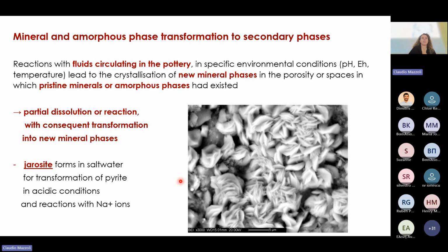And this is the case, for instance, of jarosite, which forms in salted water by transformation of pyrite under acidic conditions and by reaction with the sodium ions contained in the seawater. It's very complex, and what you get are very nice crystals observed under the scanning electron microscope, which look like roses, and there are thousands and thousands of crystals. These crystals are very important because they turn the ceramic, which was originally red, into a ceramic material which becomes macroscopically yellow. So the material can lose its color, change completely, and so sometimes this causes misclassification of the ceramic itself.